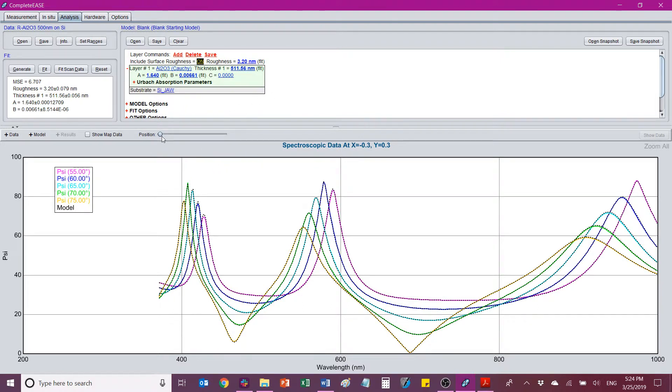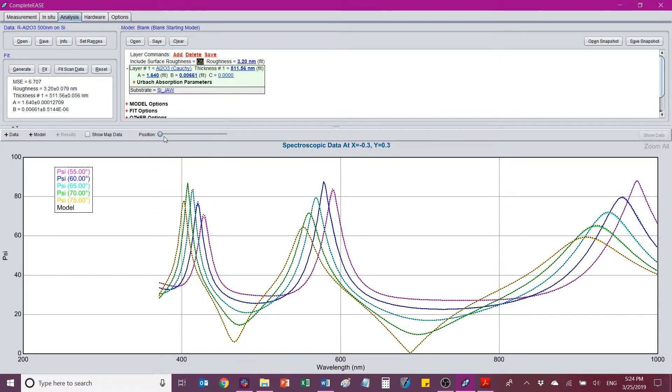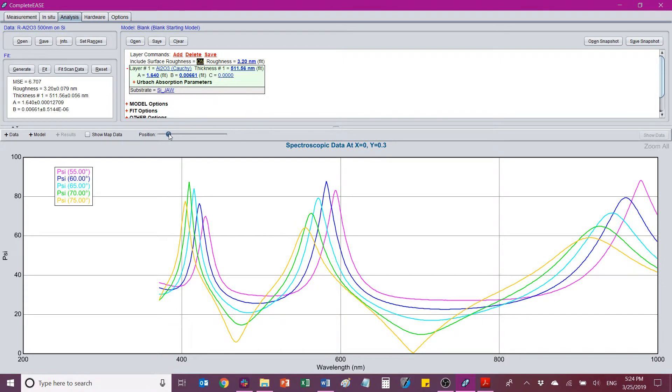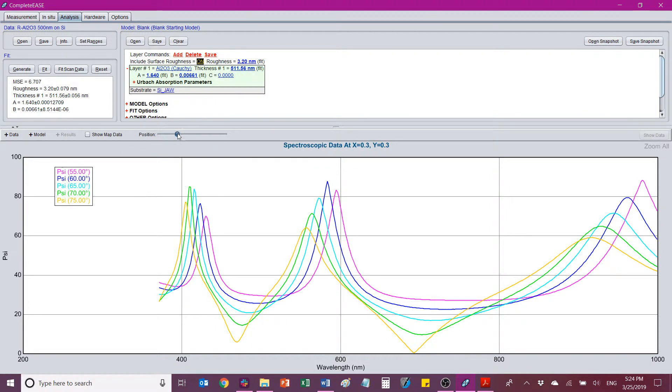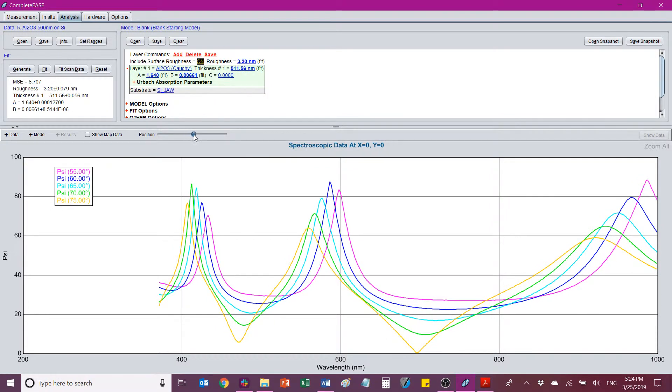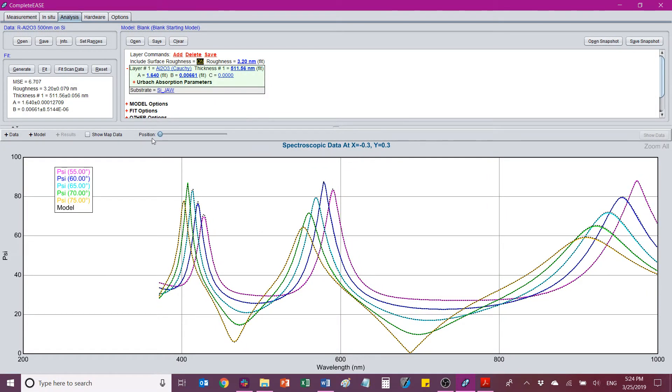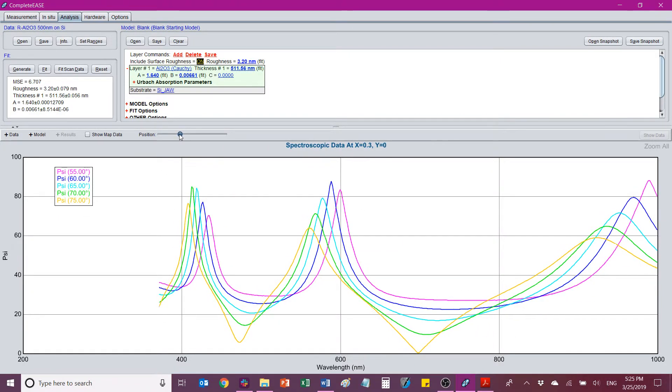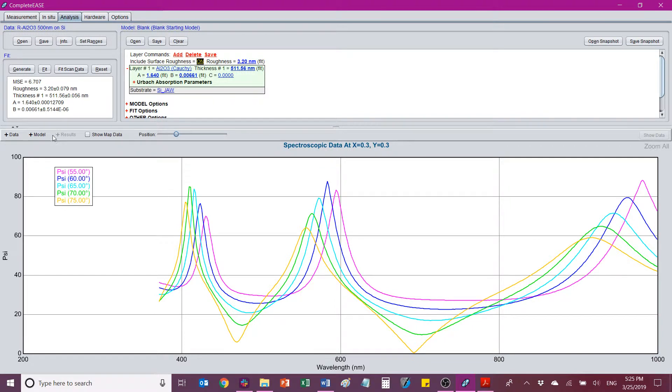Now this data file is actually not a single scan. It's actually a set of scans. So if I look at this position slider right here, this shows up when you've done a mapped scan. So you've collected a scan at a variety of points across the surface of the wafer which you have defined. And so you can create a contour map of the surface. So if I just slide through this, I can move through the data collected at the different points. And you'll see that the fit is only actually being applied to the first data point. In order to apply it to all the data points, I'll hit fit scan data right here.